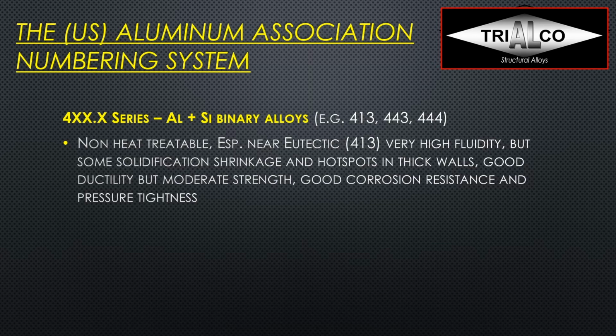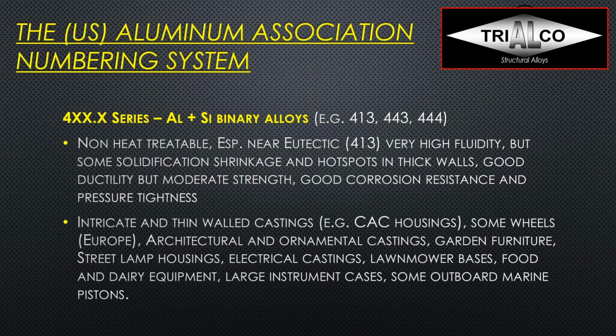We see a lot of the 413 because it's near eutectic, so it has very high fluidity, and it can just have some solidification shrinkage and hot spots and thick walls. It has good ductility, but only moderate strength without the magnesium in there, but pretty good corrosion resistance and pressure tightness. So it's used, for example, for CAC housings and things like that. Any kind of intricate and thin-walled castings, some wheels even in Europe, the smaller car wheels, architectural and ornamental castings, garden furniture, street lamp housings, electrical castings, lawnmower bases. I mean, you can see it's really a lot of different things, even some outboard marine pistons that are made from this.